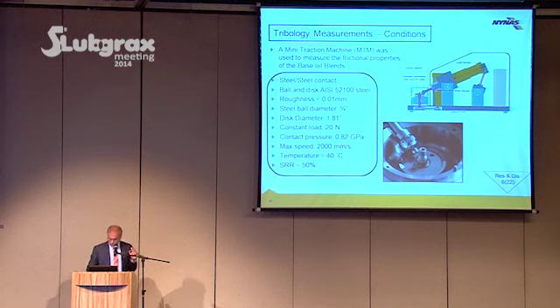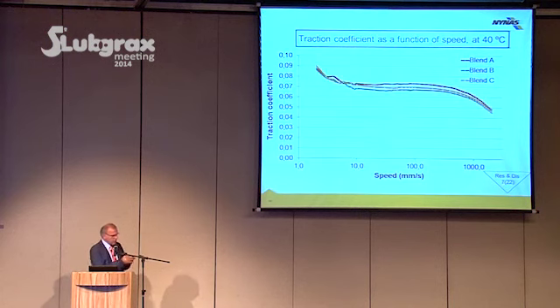all 3 base oils. What we see here is the traction coefficient, which is equivalent to friction coefficient, as a function of speed up to 2 meters per second. Blend B, which contains group 2 and naphthenic, shows a slightly better behavior. However, all these are much better than single group 1, according to our study, as well as a single naphthenic. So the combination, in fact, was better than single oil.